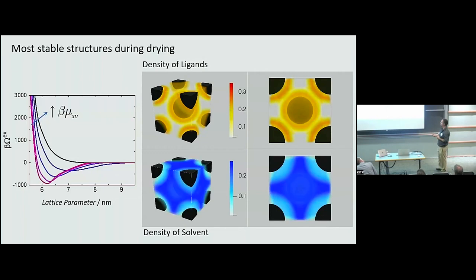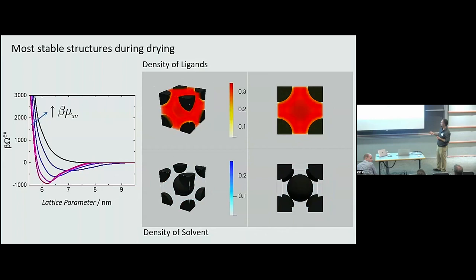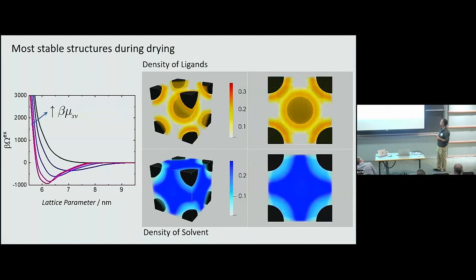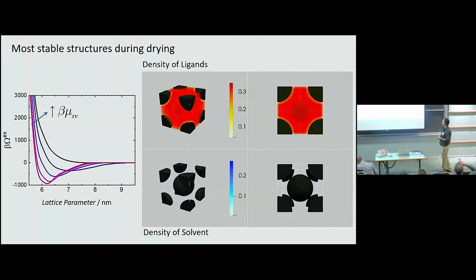And then you start increasing the chemical potential of the solvent, and this minimum will get less negative and will shift to larger lattice parameter. If you increase it too much, it will eventually disappear, and that's when the lattice is not stable anymore.